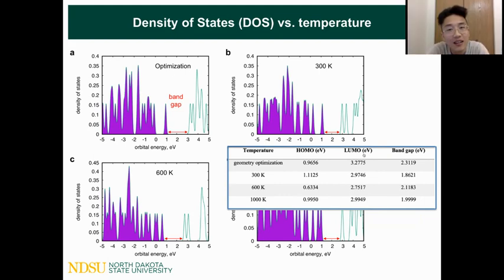But technically, you probably need to take at least hundreds of structures along the trajectory of your molecular dynamics, hundreds of random conformations. For each of them, you need to plot the density of states and then average over all densities of states. Then your density of states will be broader, and the average gap from these 100 structures at each temperature will show you some dependence on temperature.